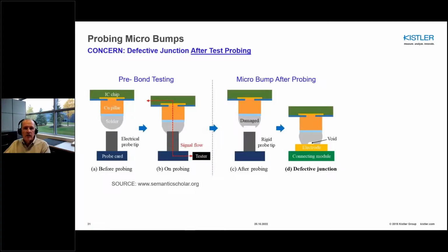A concern in testing is to perform the test without damaging the device under test or altering its performance. In this illustration, we have an electrical test being performed on a single micro bump, let's say from a flip chip circuit. On the left portion of the slide, the probe head is shown contacting the individual bump pad for an electrical test, and the result of this test is good. Electrically, this passes.